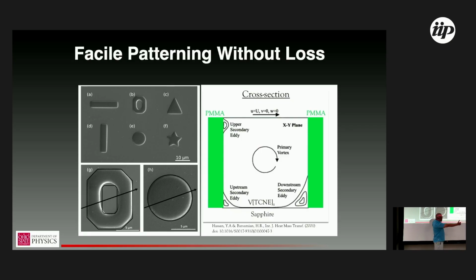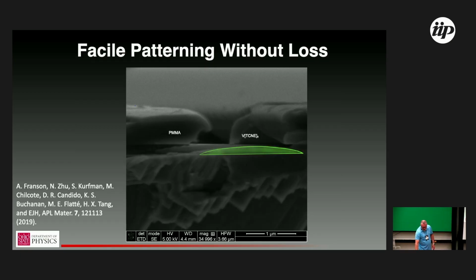but as you start making your structure wider, if you've ever gone bowling with the little bumpers in the gutters to keep your bowling ball in the middle of the lane, we have these two rails running down the side of our pattern that are more or less permanent vortices, which means it's very hard for precursors to diffuse into and then out of that region to deposit. And so that's what gives us this tapered cross section, and that's a sort of fixed width set by the height of the PMMA.